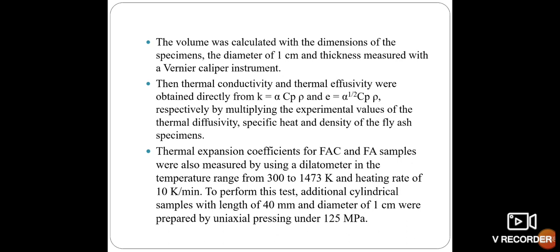The volume was calculated with the dimensions of the specimens, the diameter of 1 cm and thickness measured with a vernier caliper instrument. Then the thermal conductivity and thermal effusivity were obtained directly from the equation K equals alpha Cp rho, and another equation, effusivity, E equals alpha raised to 1 by 2 Cp rho, respectively. Through these equations, by multiplying the experimental values of the thermal diffusivity, the specific heat and the density, the properties of the fly ash specimens were determined.